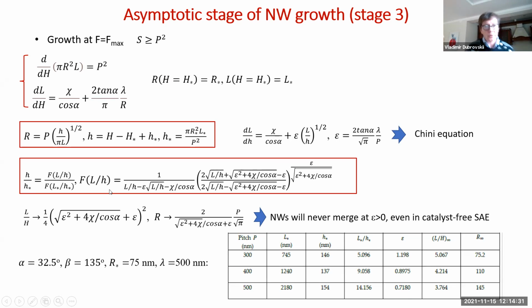And the solution of this equation is non-linear, so it's not very simple. But of course, I can plot the graphs, and what I can also see from the solution is that in the asymptotic stage, where the time goes to infinity, L over H tends to a certain value which increases with epsilon. So meaning that the larger the lambda, the larger is L over H, and it decreases with the pitch. So finally, the nanowires grown in the smaller pitches will become taller, which is quite impressive and interesting.